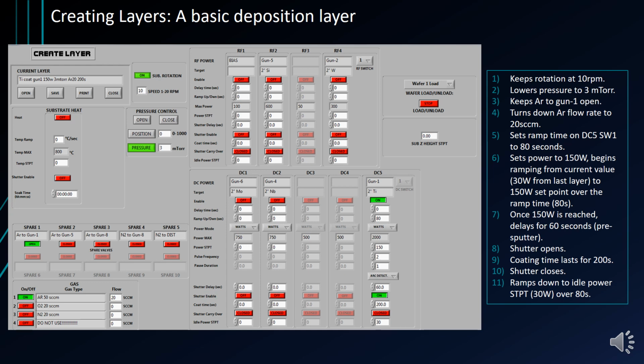Now there's a ramp time of 80 seconds on DC5, and I've set the power to 150 watts. This is in accordance with a general rule I follow for ramping rates, which I will explain later. After the 80 seconds is up, there will be 150 watts applied to the target. Then a 60-second shutter delay is set to clean the target surface and let the target reach a better thermal equilibrium and stable sputter rate. After the 60-second shutter delay, the shutter enable is on, so the shutter will open. It will remain open for the coat time of 200 seconds.